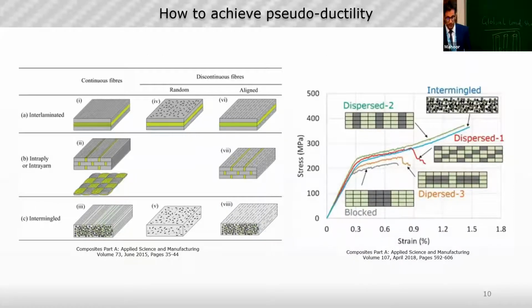Different approaches of hybridization could create different grades of pseudo-ductility. Here we see a schematic of how many different hybridization approaches generate pseudo-ductility. This approach, the hybridization, is good because it separates the fracture process. So isolate the low elongation fibers together with the high elongation fibers and isolate the fracture process. It's one of the base concepts to generate this plateau stage, progressively and stepwise, until the final failure of the material.